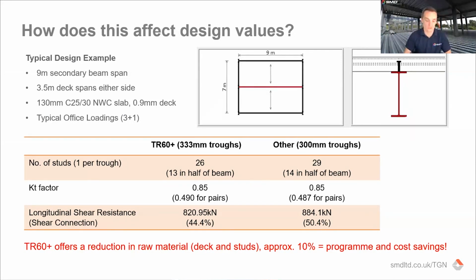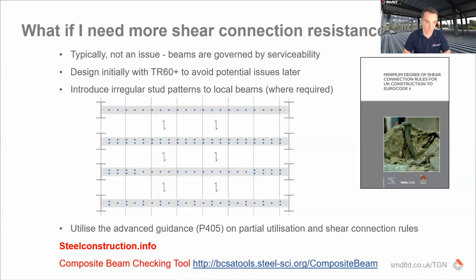Just worth considering. There are instances, so this is what I wanted to lead then on to. There might be instances where, because of those extra few studs, it will work with another product and not at 333mm centers. And there's a number of answers to that. It's not common that is an issue, because they're quite regularly governed by serviceability, the beams, depending on your lengths and your loads. So there are cases where it may be. The recommendation would be design initially with the worst case spacing. So in this scenario, it'd be with a TR60 Plus, and that then gives you the flexibility should you wish to change spec later.